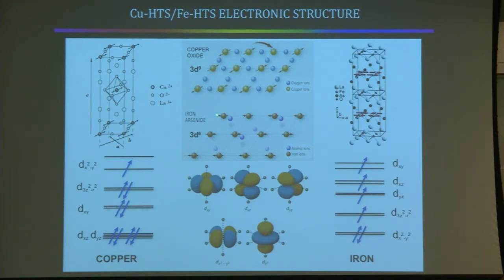Now, iron superconductors, we have iron and selenium, or iron and a chalcogenide, in a slightly different symmetry lattice. And three-dimensionally, the actual crystal fields from the chalcogenides or the pnictides are cubic. So they also lift the degeneracy of the d orbital on the iron atom, but they do it in the opposite direction. So the top of the manifold now is dxy, and below it are dxz and dyz, and right down at the bottom is dx squared minus y squared. It's like you take the copper manifold and turn it upside down.